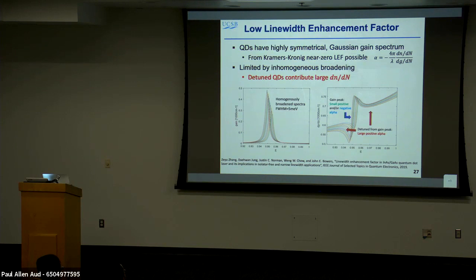So theoretically, why is that? Well, quantum dots have, ideally, a delta function gain spectrum. And then Kramers-Kronig says that the phase term should go through 0 right at that delta function. So if you look at calculated many-body calculations, and Wang Chao's been doing those for us, these are all individual dots of different sizes. So they're all fairly narrow, maybe 5 meV. But you put them all together, and they're broadened because not all the dots are the same size. What you calculate is that the phase change due to that is shown here.